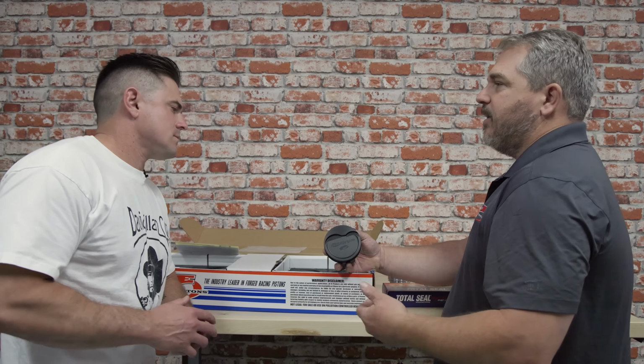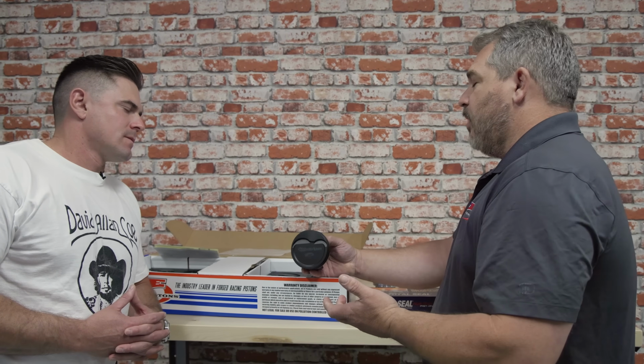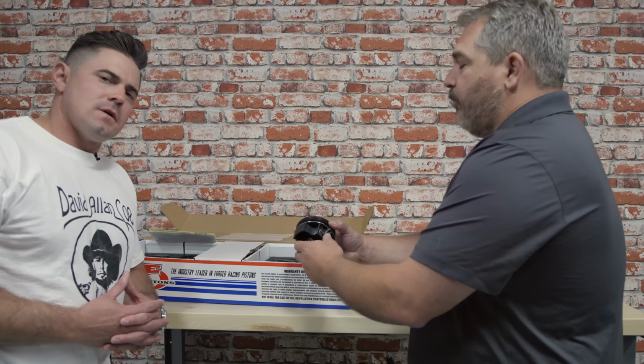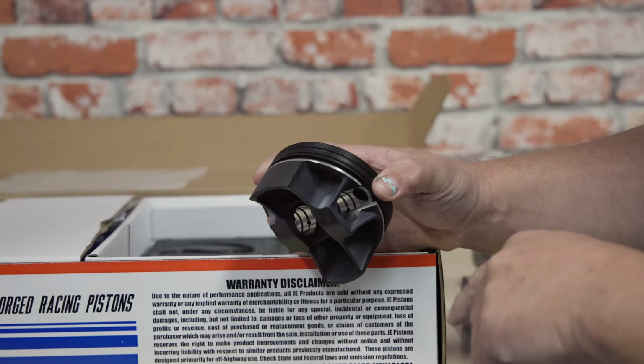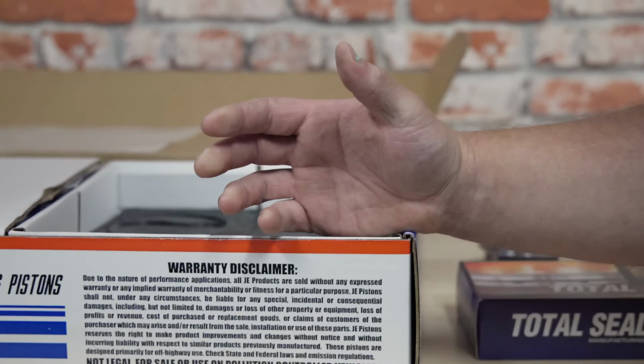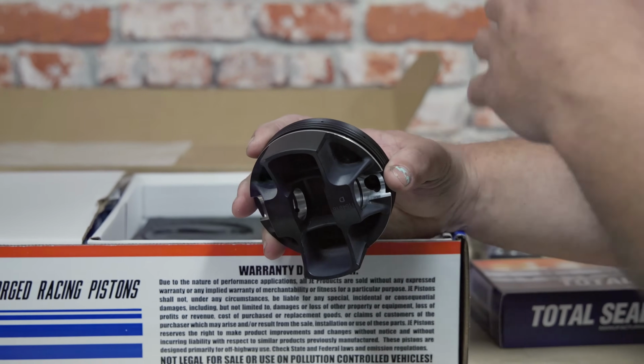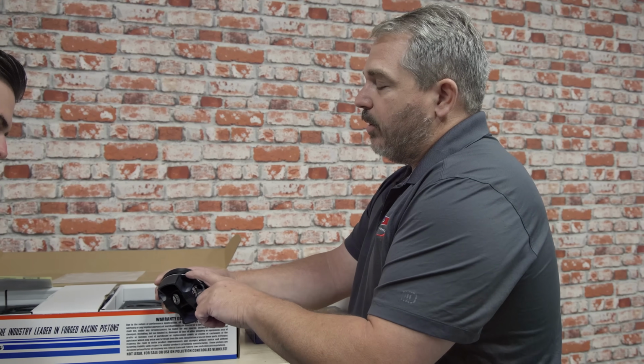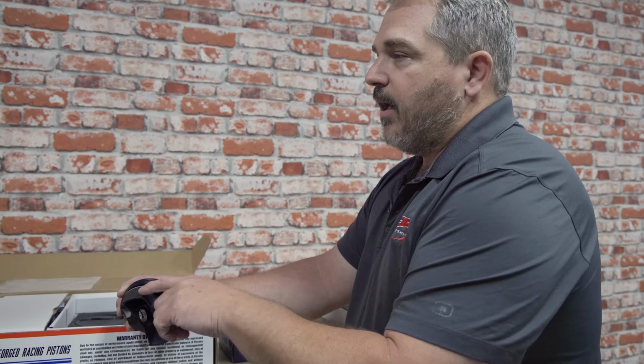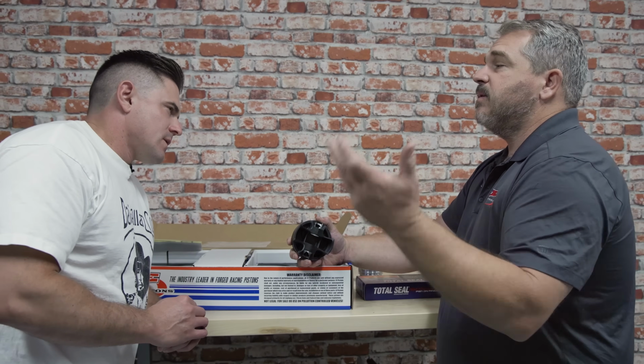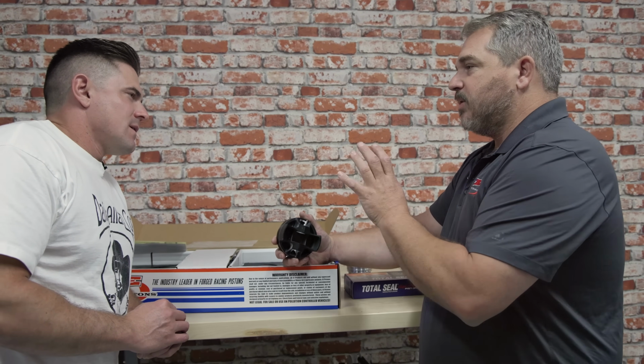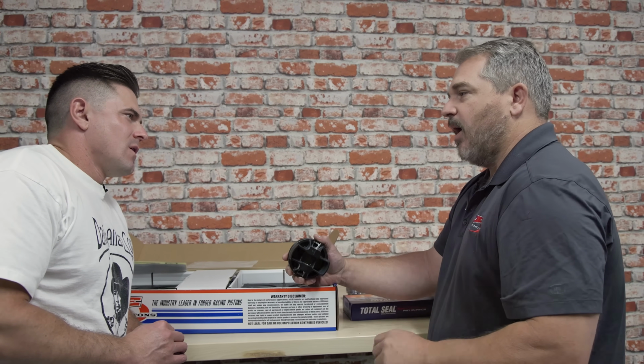So traditionally hard anodizing isn't used on a street engine, but the way we fix that is by allowing the heat out. Our process is to dunk the whole piston into a tank, it's anodized, and then it comes back out and gets machined. From the third land, or your oil land, down, we machine the turn diameter, or the cam and barrel shape that we talked about earlier. So we actually machine the anodizing off the piston. That gives the heat the ability to escape the part so it can cool off. The aluminum doesn't just heat soak in that shell of anodizing over time. As the piston heats up and cools down, you can get heat out and you have oil that can run on there to also help cool the parts.